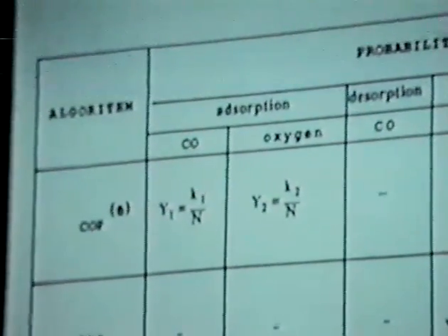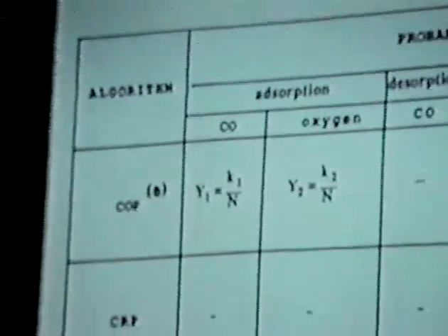These are some details on the simulation. I'll go quickly. The way to do this is to take these rates of reactions and normalize them by the sum of all the rates of reaction by this expression here, to obtain probabilities. The interesting thing is that we can actually get numbers that are based on experimental work and not only simulations here. And we also can look at the effect of nearest neighbors. These are several algorithms in which we're looking at different, this is collision probability and so on, I'll explain that later. But the fact that a molecule can land and look at the nearest neighbors and react with them if there is a site that is occupied by the same molecule or a different molecule is accounted for by this factor here.